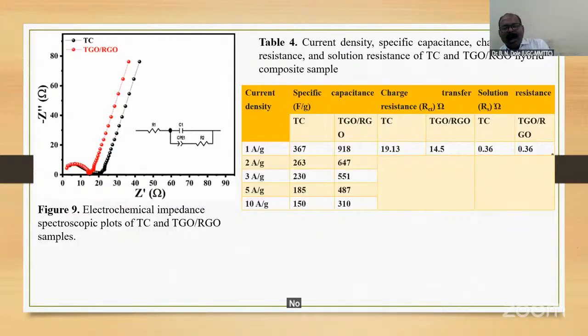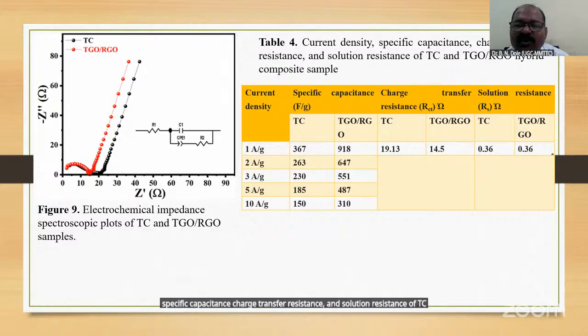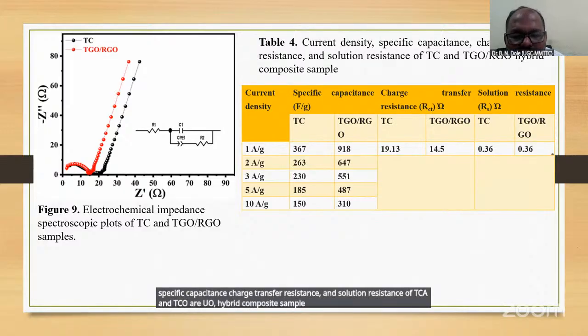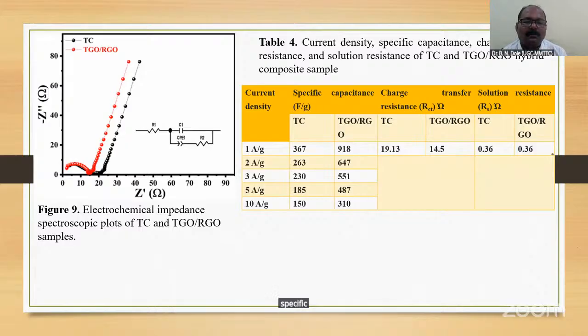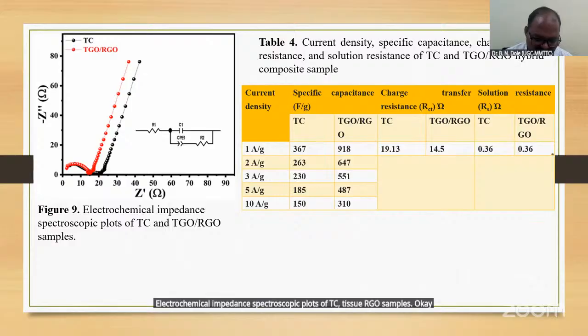Now, this is the current density, specific capacitance, charge transfer resistance, and solution resistance of the TC, TGO, and RGO hybrid composite samples. Specific capacitance in farad per gram, charge transfer resistance, and solution resistance, all this. Electrochemical impedance spectroscopic plots of TC, TGO, and RGO samples. Okay, now these are the plots.